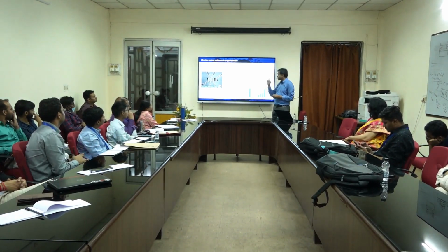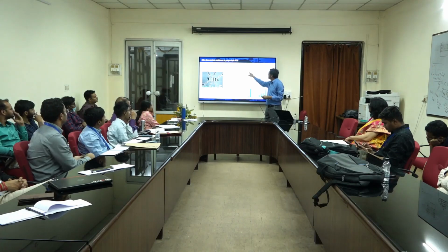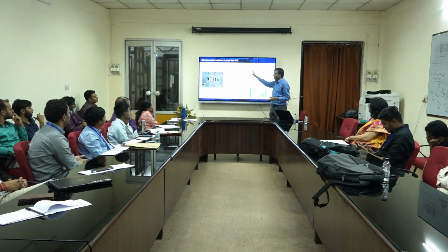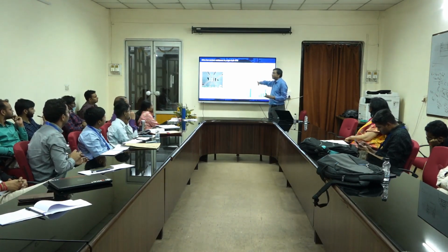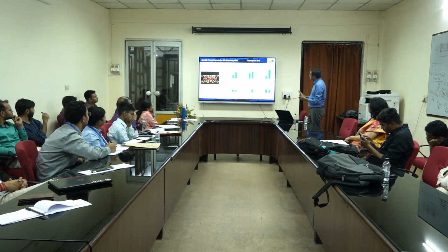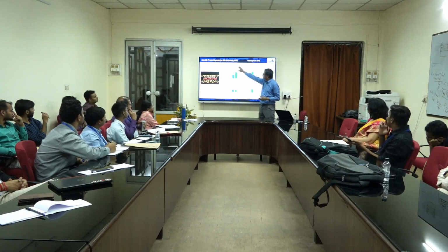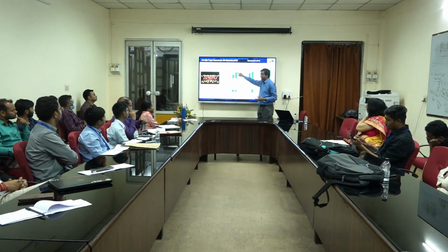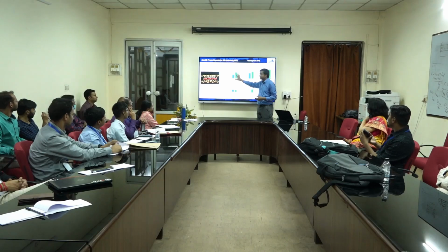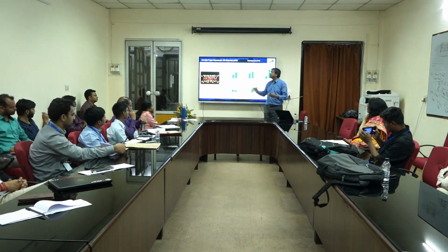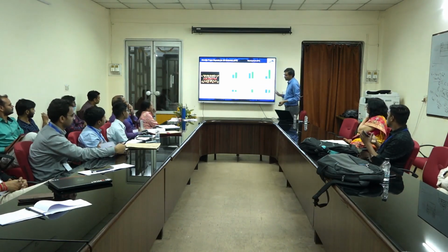Now, one thing I have not mentioned in this slide is that each of these dopants does not have a similar amount of doping. Because we did the CVT growth, you never knew whether niobium was 100% activated versus vanadium 90% activated. We do not have an idea on that. At the very beginning, I showed another slide which was too much, and I did not discuss it. We have done some characterization called ICP in order to find out the dopant concentration. You can see the niobium doping percentage is higher compared to the tantalum one and the vanadium one. But this still does not tell me what the activation is. Just because more dopant is present doesn't mean all of them are activated, and we have no clue about that. It's very difficult to find that out.